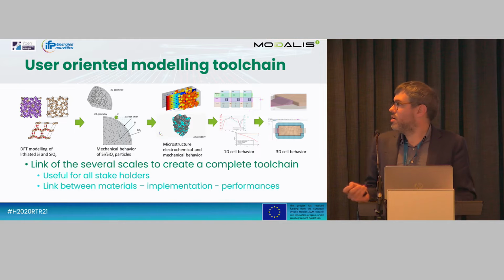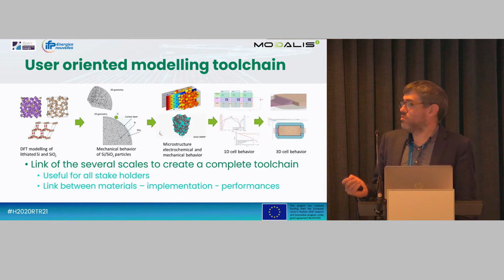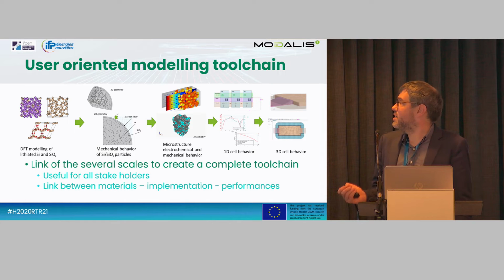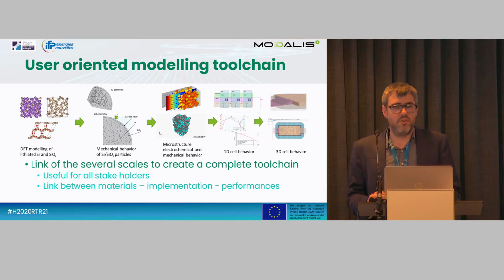into mechanical particle behavior, into DEM or FEM at the electrode level, and finally implement it into cell level. So this cell level is fit for aging behavior, so it's interesting for us to use that for 10 or 20 years simulated in our systems, and also for 3D cell behavior, where you can see especially the design of your cell and make sure that you have homogeneous behavior inside your cell.